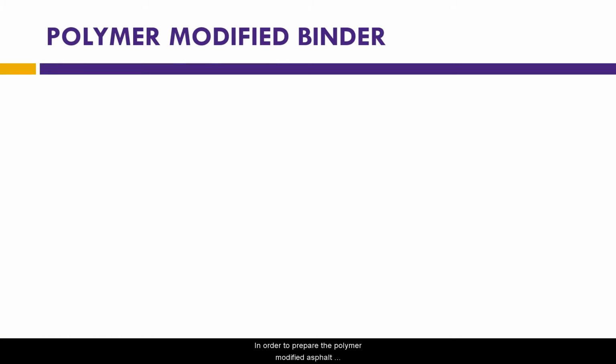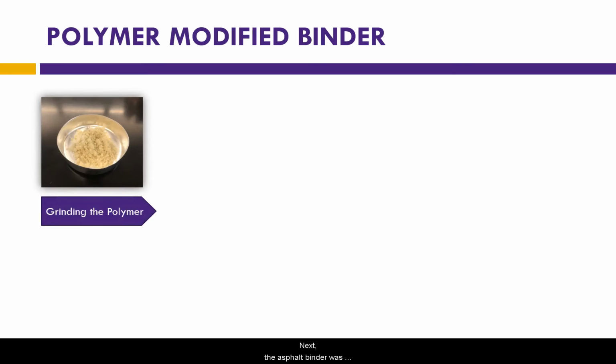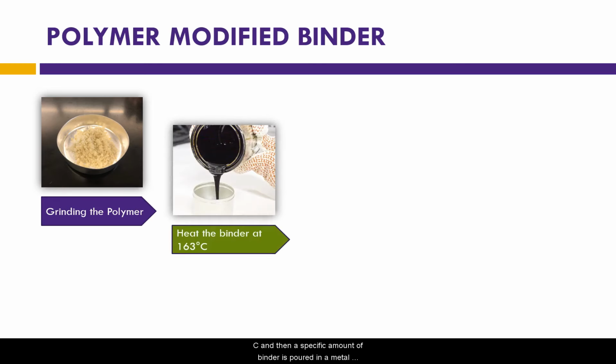In order to prepare the polymer modified asphalt binder, first we need to decrease the particle size of the polymer. A grinding machine with 24,000 RPM was used to decrease the size of the polymer. Next, the asphalt binder was heated in an oven at a temperature of 163 degrees C, and then a specific amount of binder is poured in a metal can.